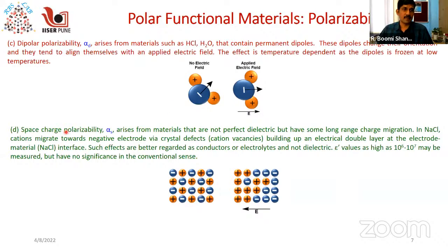The final polarization is called space charge or interfacial polarizability. This space charge polarizability happens when the charge carriers at the electrode material interface migrate. This typically happens because the electrical charges at the electrode material interface will experience an enormous electric field during the application of an electric field. Because of that, the ions will tend to migrate very rapidly. During the reversal of the electric field, the migrated charges will not go back to their original state, because they are trapped within the system. This is because of the friction between the electrode and material interface, so the ions will not go back to their original state.